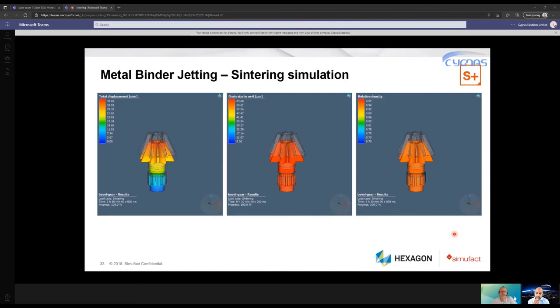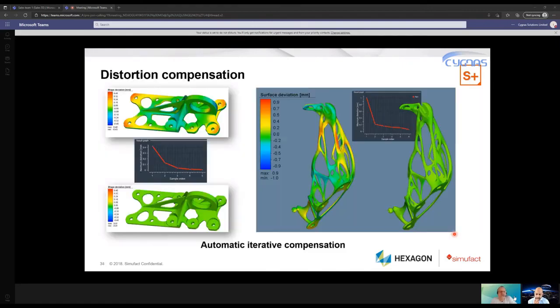So this distortion compensation is really like the killer functionality of the software. You can do it in an automatic iterative way, which really gives very good results. You can almost drive your distortion to 0 by applying localized pre-distortion to your part.